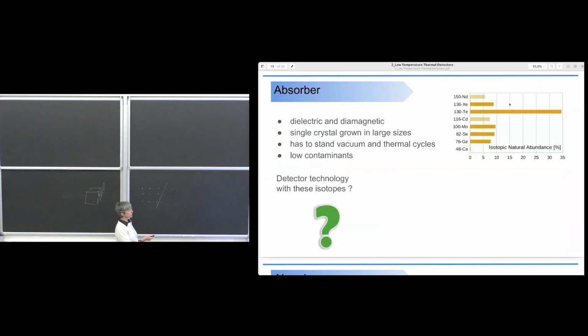Do you remember this plot I showed you yesterday? It's the plot of double beta decay candidates, already what is called the golden selection. Those candidates have a high Q value, and we have seen that a high Q value means both a high transition probability, because the phase space increases with the Q value, but also some advantages from the point of view of the background, because you have less background at high energy, in the region where you look for your signal.